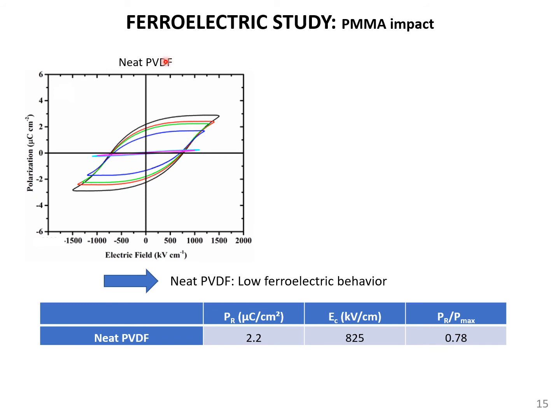First of all, we make a comparison in the case of the neat PVDF as obtained by extrusion calendering by reporting the polarization value, particularly the remnant polarization value and the coercitive electric field required to get this polarization in the case of neat PVDF. You can see from the graph that you obtain a very low ferroelectric behavior.